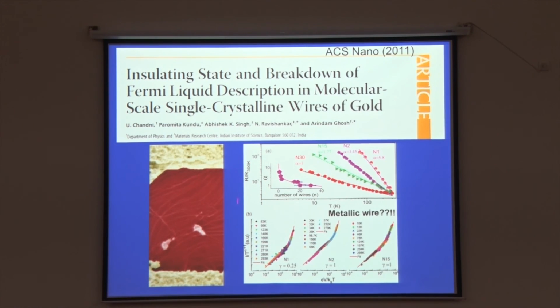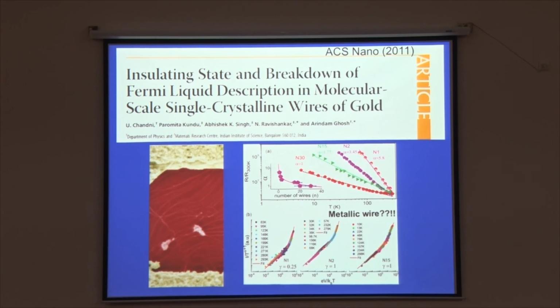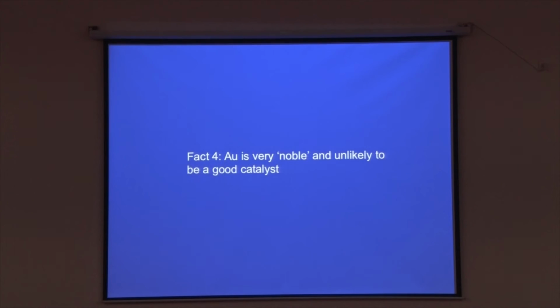What I am plotting here is resistance versus temperature. For a metal, you would think that the resistance would increase as you increase the temperature because of the scattering process. On the other hand, what we are seeing here is R normalized to the room temperature resistance basically decreasing. So there is something new and interesting going on here, and we get some very interesting scaling behavior that tells you that there is a breakdown of the standard description that we have for these kinds of metal wires.